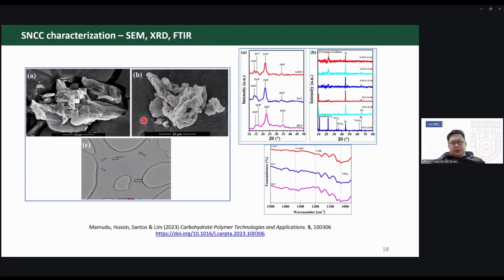Once we made the nanocellulose and sulfated nanocellulose, we deposited them into the epoxy at different percentages by weight. So the number 10 means 10%, the number 20 means 20%. The ones at the bottom are the normal nanocellulose, and the ones on top are the sulfated ones. This XRD was taken after 30 days of immersing the coated samples.